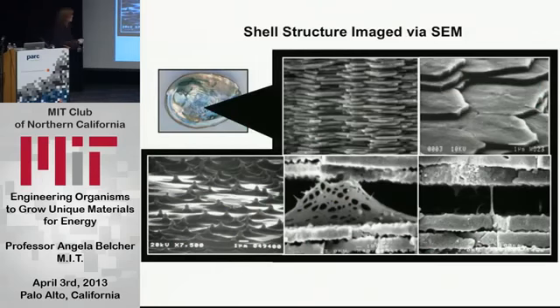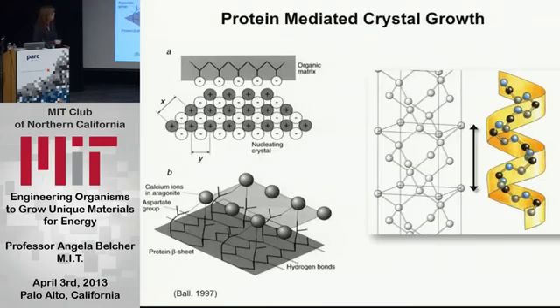And if you look at the scanning electron micrograph, you see these plates, and in between these plates are these organic matrices. And these organic matrices are the ones that actually nucleate the right crystal structure. Aragonite calcium carbonate comes in 3 different crystal structures, and the abalone chooses the metastable crystal structure. And how does it do that? Well, it has a DNA sequence that codes for a protein sequence that allows it to be nucleated and to grow and to be the major structure. And it actually has no perfect cleavage plane, so it's a much more stable structure.